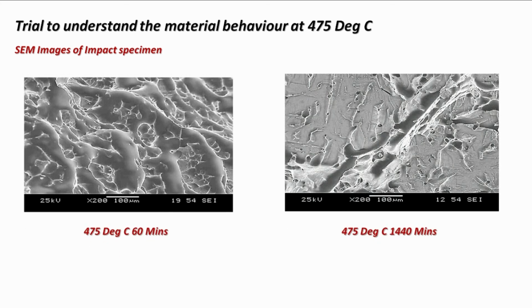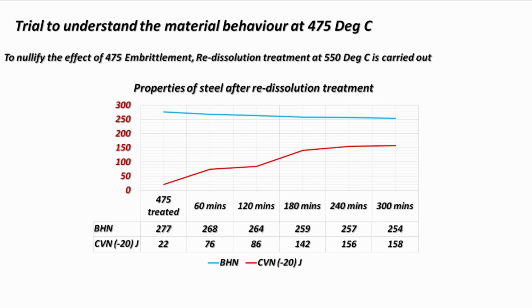So to validate that further, the fractography images are shown, which clearly show brittle fracture. So to nullify the effect of 475 embrittlement, between 500 and 600 degrees Celsius, we carried out redissolution treatment at 550 degrees Celsius. So you can see there is a gradual recovery in the impact toughness of the material from 22 joules to 158 joules.